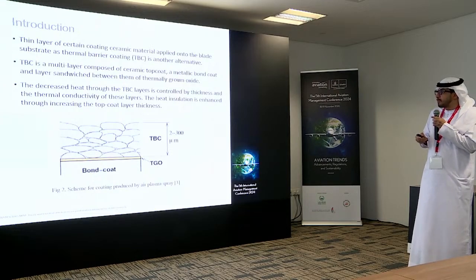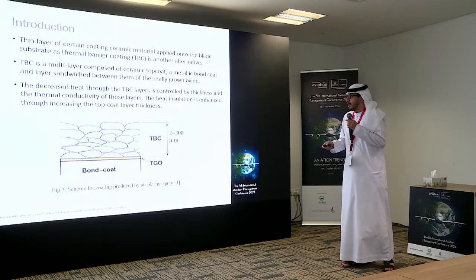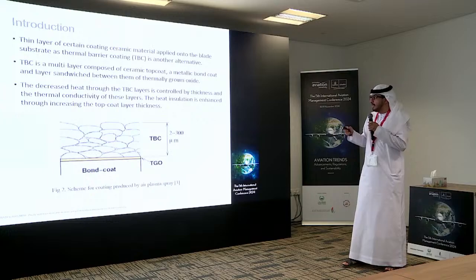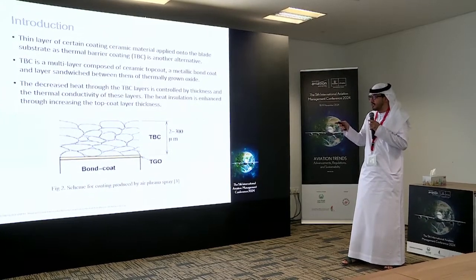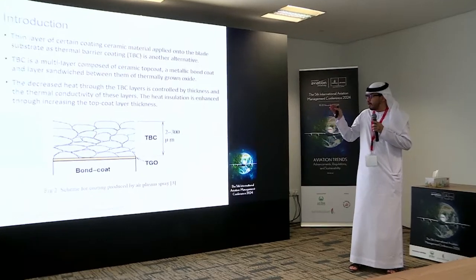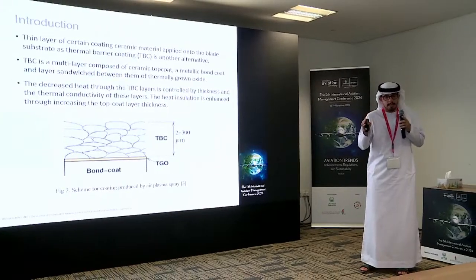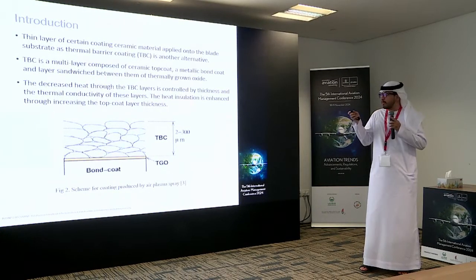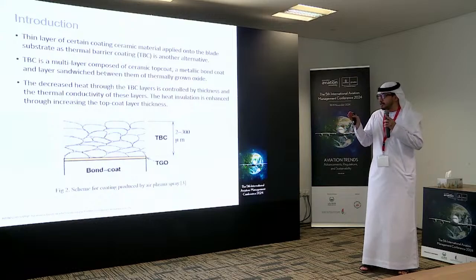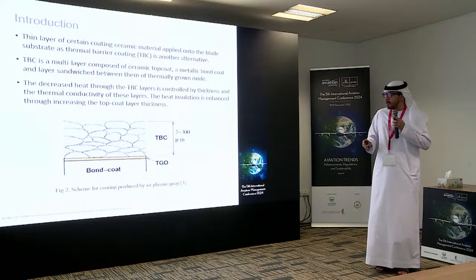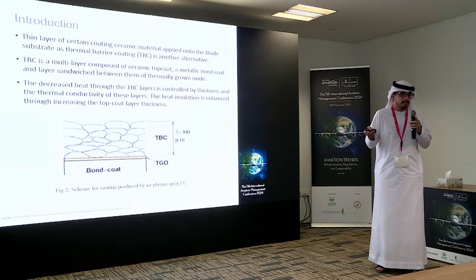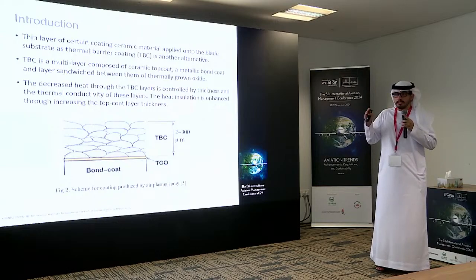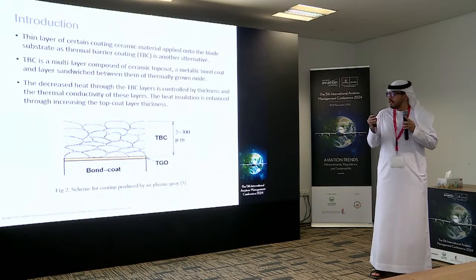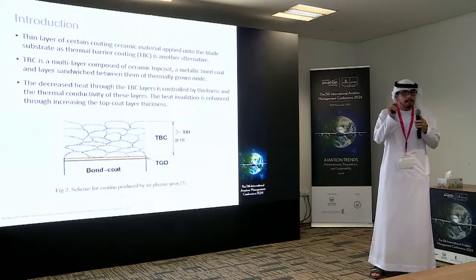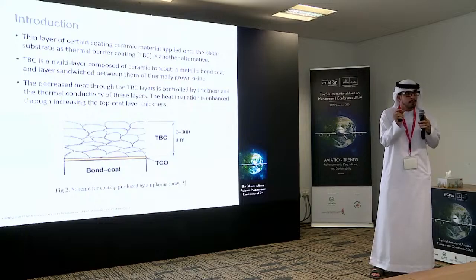The heat reduction through the thermal barrier coating is controlled by the thickness and the thermal conductivity of these layers. The heat insulation is enhanced by increasing the top coat layer thickness. As you can imagine, if we apply the thermal barrier coating on the turbine blades, it would decrease their temperature, and by that we can ensure that the turbine will operate within safety limits. However, we cannot increase it as much as someone might suggest. There should always be a limitation to our design and thickness. For example, if we increase the top coat layer, it will cause potential thermal stress. This stress will lead to cracks in the blade itself. So a balance should be taken into consideration.